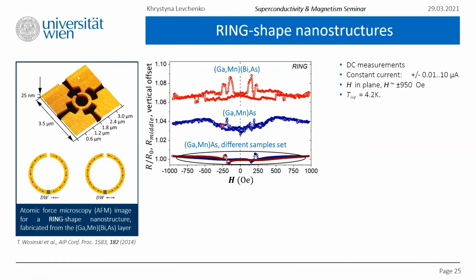Before going into details, it was shown that gallium manganese arsenide thin layers grown under compressive strain are simple single domains of the size of hundreds of micrometers. This model, where we assume that we have a single domain that could be separated by a domain wall by introducing a slit here, is applicable. So the 4 contact pads were all supplied with ohmic contacts, and the current was flowing throughout all the ring, while the resistance was measured through the middle segment.